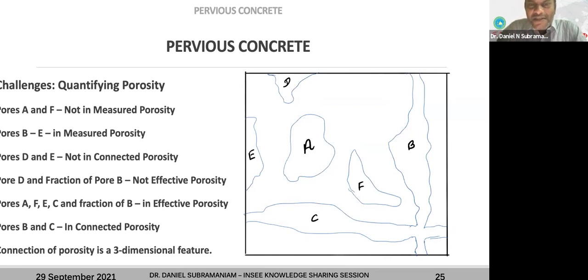The second one, if you take the pores D and E, yes, they will be exposed to the surface, so they will be included in the measured porosity. But compared to B and C, D and E are not going to contribute to permeability because they don't let the water transfer. So it will let the water enter, but it's not going to transfer water. So it has to be B and C, but even C is not going to contribute to permeability because it's on the cross-sectional side. It's going to be perpendicular to the fluid flow that we are going to consider. So only one type of pore is going to actually contribute to permeability. So how are we going to do that, right?